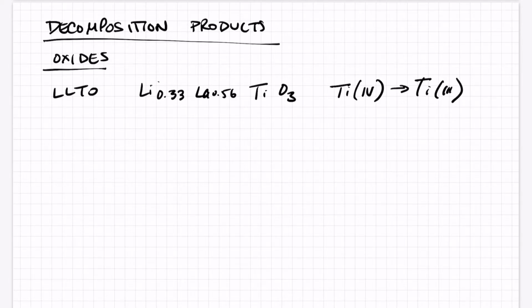So titanium being a 4s2 3d2 electronic configuration element, in the oxide state, it tends to be a +4 state, so that it gets back to a nice closed shell system. It can be changed to titanium 3+ with some holes for charge balance.